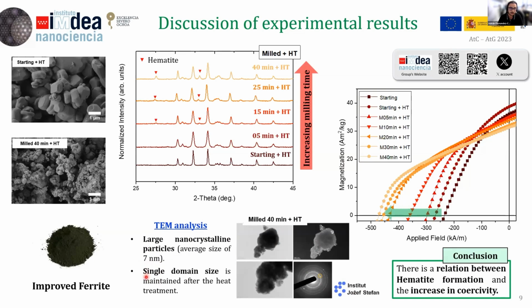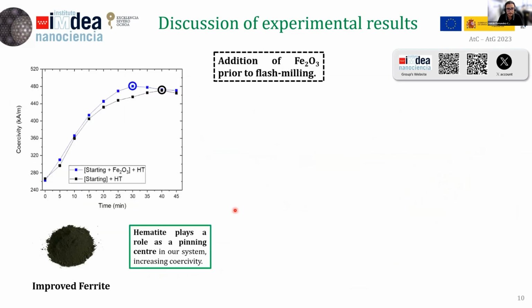Thus meaning that we managed to retain the single domain size even after the heat treatment at really high temperatures for really long times. So for that, if we manage to do this relation between the formation of hematite and the increasing coercivity, we try to be sure that this relation is correct by adding a little bit of hematite prior to the flash milling